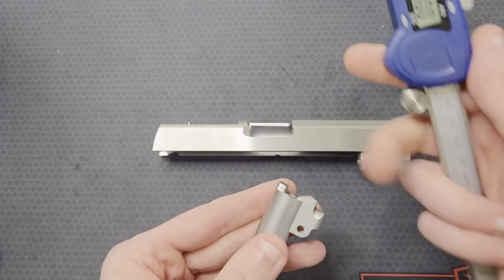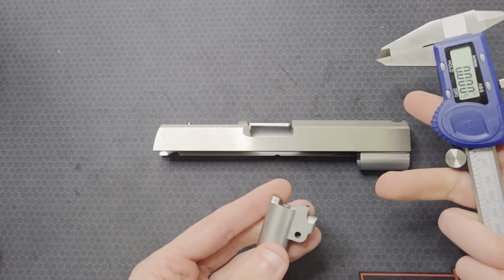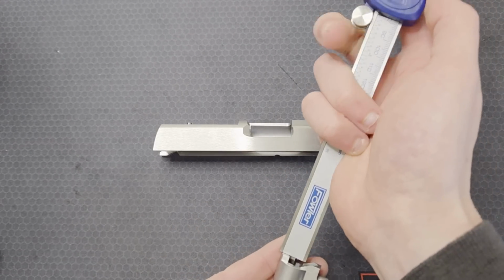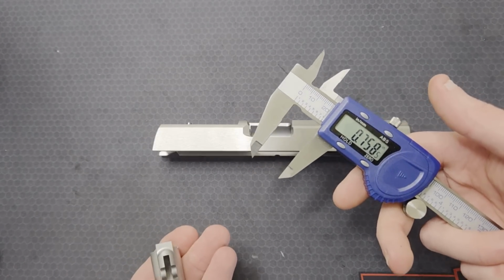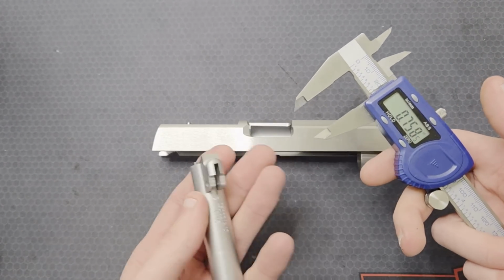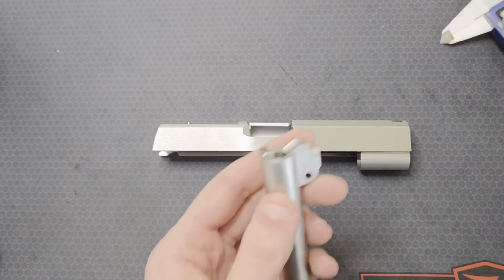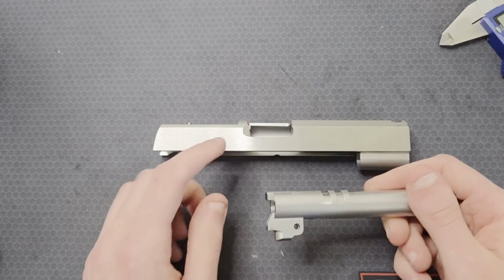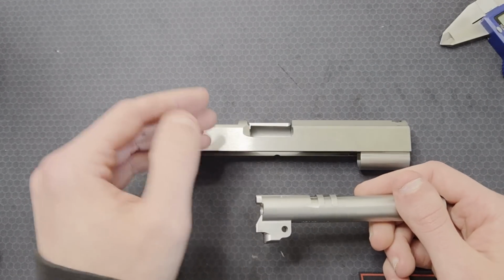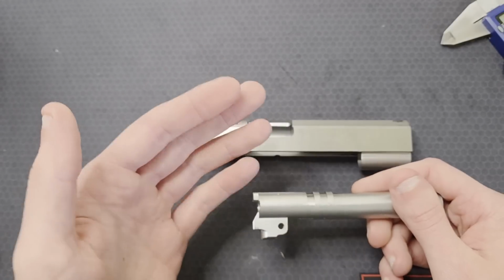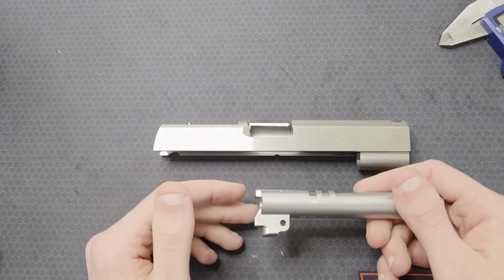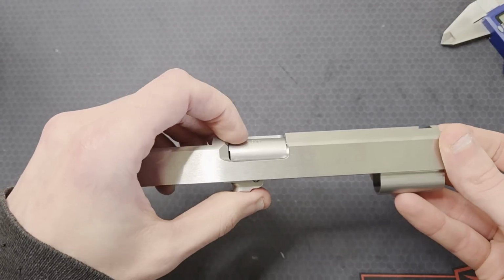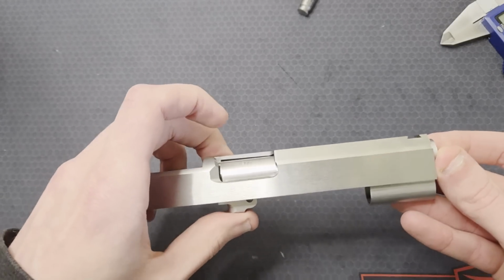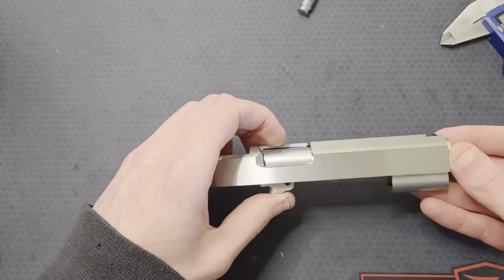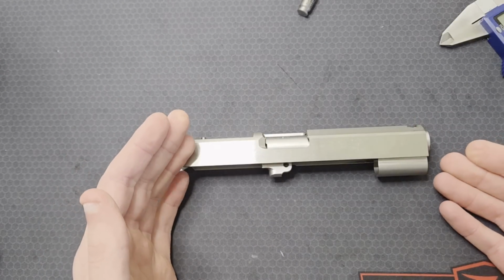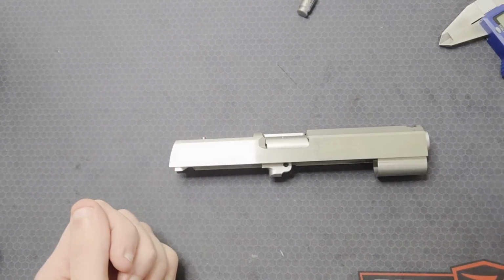I've fit the hood to my slide, but I haven't adjusted headspace at all on this chamber. My headspace is 758. So the chamber is already deep enough. My guess is that the chamber in the Atlas barrels is cut to a depth so that it doesn't need to be reamed after it is fit to an Atlas slide. This would simplify and speed up their pistol building process. It locks up with the go gauge and won't lock up with the no-go gauge. So I'm going to assume my chamber and headspace are good to go.